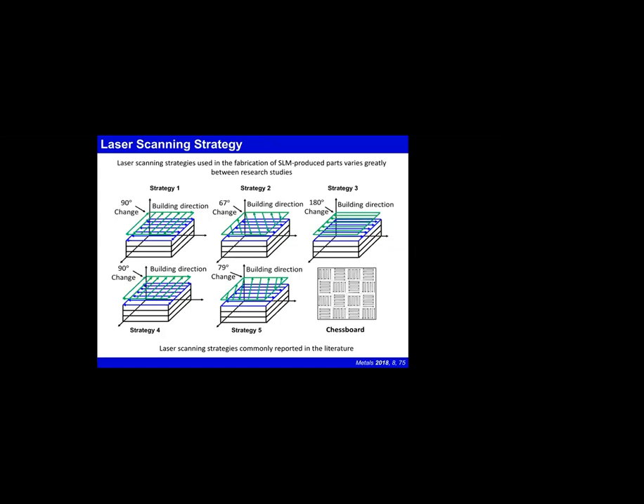We call it laser scanning strategy. You can see in this case, the laser goes in this way, then comes back and here. So there are different ways you can use your lasers. Here you can see the last one, chessboard. If you use this kind of laser processing, then what do you get? Though you will have anisotropy, it will be very local in region. So anisotropy as well as inhomogeneity in the material due to thermal stresses or compositional variation may be reduced if you use this kind of laser scanning strategy.